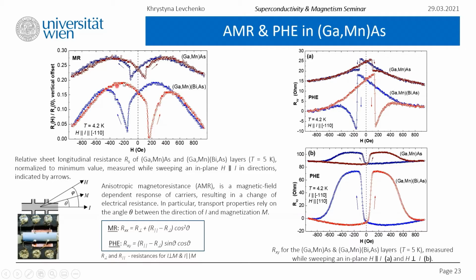So what do we see? That after high enough field is applied, magnetization vector in the layer is forced to be directed along the external magnetic field. And it typically is shown with a negative slope curve in, for example, magnetoresistance. So the full ferromagnetic order of the gallium manganese arsenide and gallium manganese bismuth arsenide spins in low temperatures below some critical point, which is a Curie point, is characterized by the negative magnetoresistance due to the suppressed quantum interference contribution to the resistivity, for example, which is caused by the effect of weak localization.